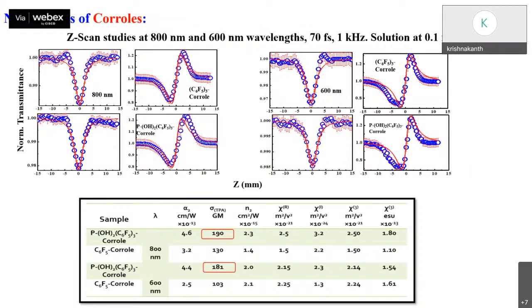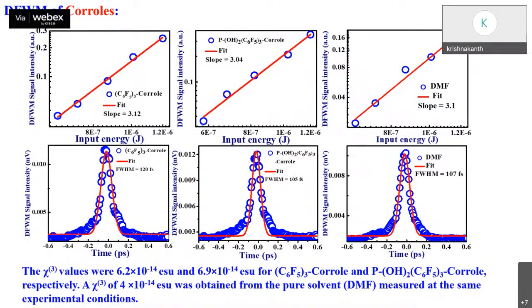From this spectra, we have a quite strong two-photon absorption cross section from the phosphorus corrole system. And degenerate four-wave mixing shows it has a fast response of 105 femtosecond full width at half maximum, and the log-log plot shows that it is a Chi3 process from the slope of 3.1.